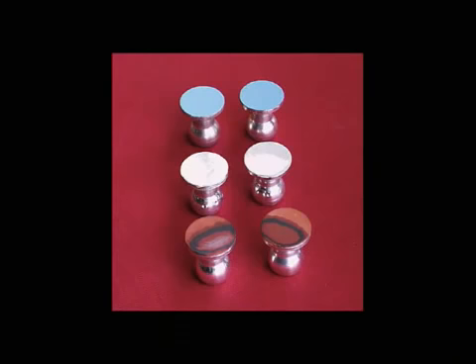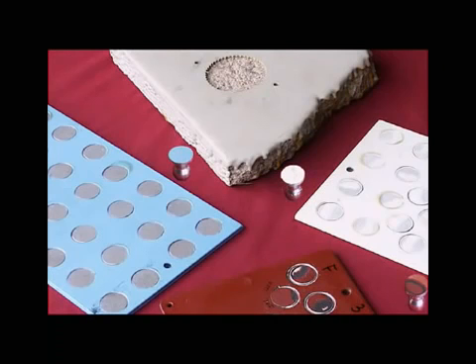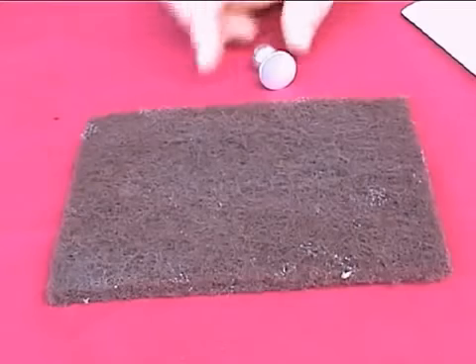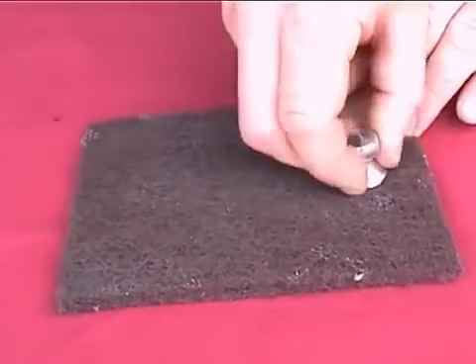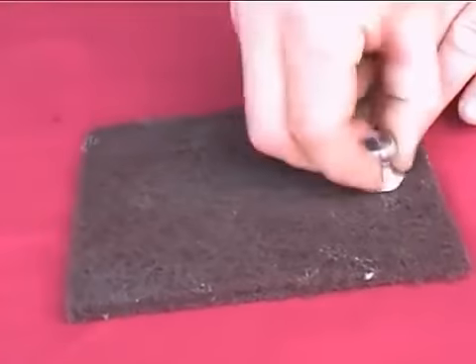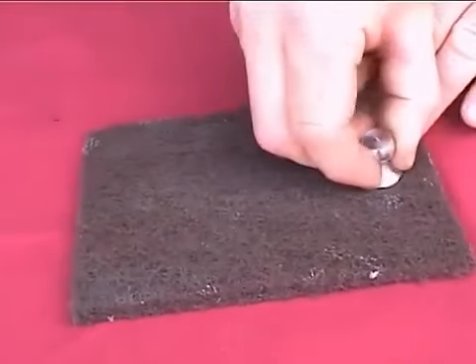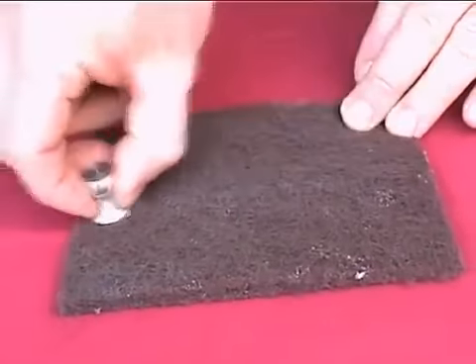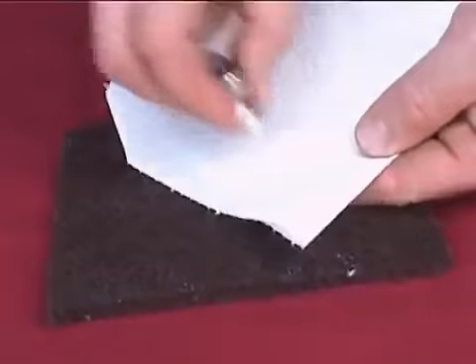The goal of any adhesion test is to determine the pressure at which an adhesive failure between layers or a cohesive failure within a layer occurs. To ensure pull-off tests are meaningful, preparation of the surfaces to be adhered is critical in facilitating adhesion between the dollies and coating. Lab tests have shown that for aluminum dollies and the Araldite adhesive, surfaces prepared with a 3M Scotch-Brite pad demonstrate strong, reliable bonds. Any residue generated by the dolly preparation method should be wiped away with a dry, clean cloth or paper towel.